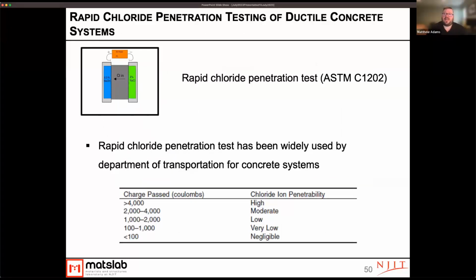One thing we wanted to take a look at is the rapid chloride penetration test. As I mentioned, this is a test that's often used because it's quick. Typically what we look at is the amount of charge that gets passed across a concrete sample, and that's related to how likely it is that chlorides will move through that system in a way to cause corrosion. Once you're getting above about 2,000 coulombs passed, that's when you really need to start worrying about corrosion possibly happening in your system at an